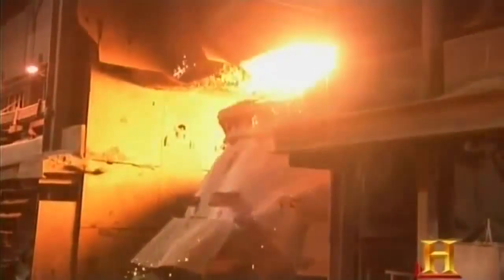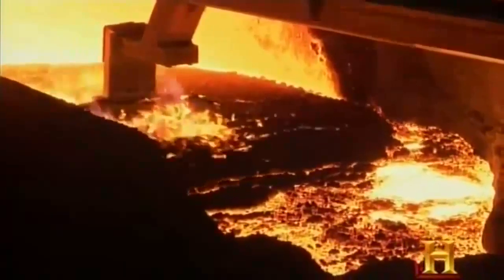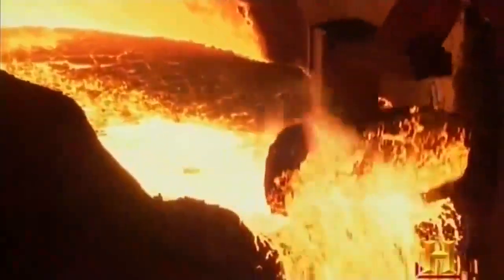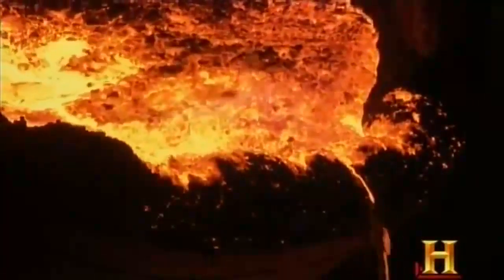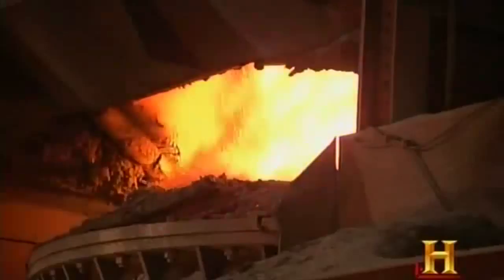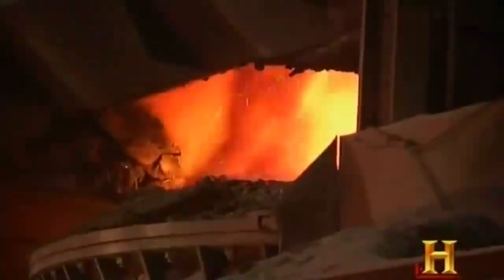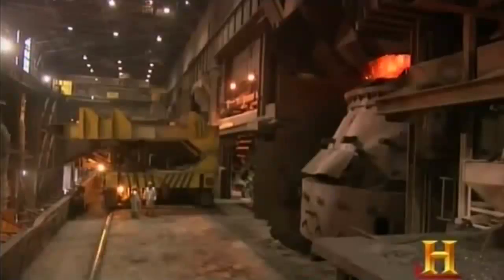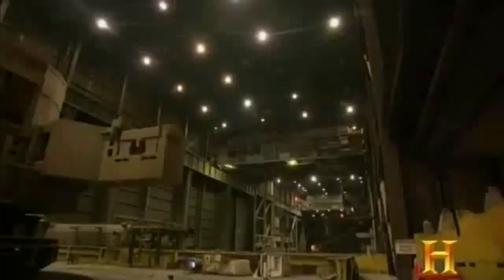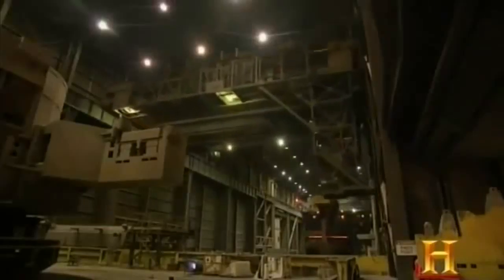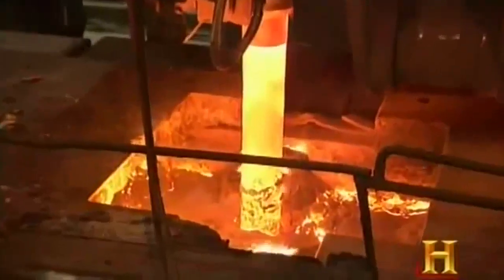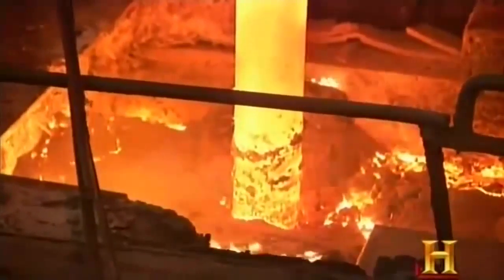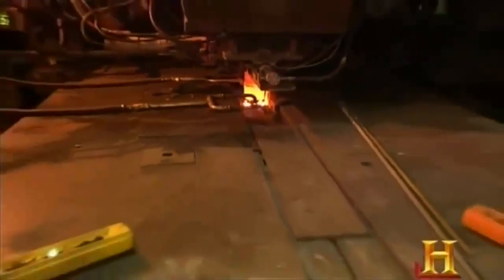In addition, the steel shop lines the bricks with a layer of a steelmaking byproduct called slag. This includes impurities such as carbon, silicon, and various oxides. About 30 years ago, the furnaces lasted about 700 cycles between rebricking. Now we're able to make between 20 and 40,000 heats on a furnace lining by just using the waste material to coat the brick. After the oxygen furnace, the slightly cooler steel will be further refined and transported in other brick-lined vessels before being allowed to solidify in a casting mold.